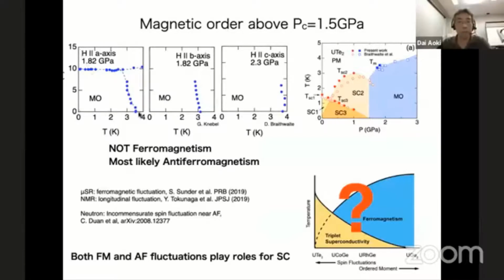This is the H versus T phase diagram for the A, B, C axes above the critical pressure. You can see the magnetic order temperature Tm is decreasing with field, or increasing like this, or vertical. So this phase diagram cannot be explained by ferromagnetism. Rather than ferromagnetism, I believe it's close to antiferromagnetism, or at least it's not simple ferromagnetism.